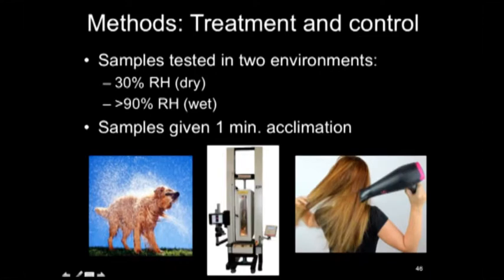So we measured samples in 2 different environments: at very high humidity, above 90% relative humidity, and at dry conditions, 30% relative humidity. And we gave samples at least a minute to acclimatize, and these were tested inside of environmental chambers where we could adequately control the humidity using evaporated water in the air.